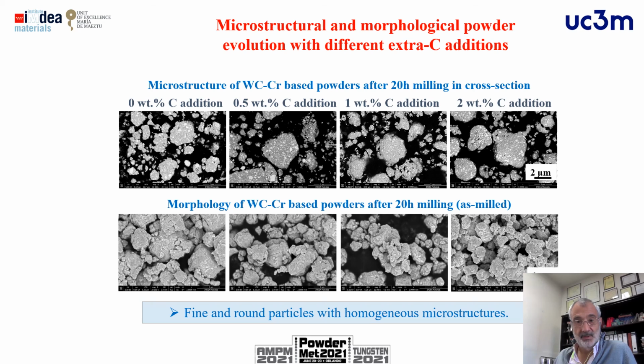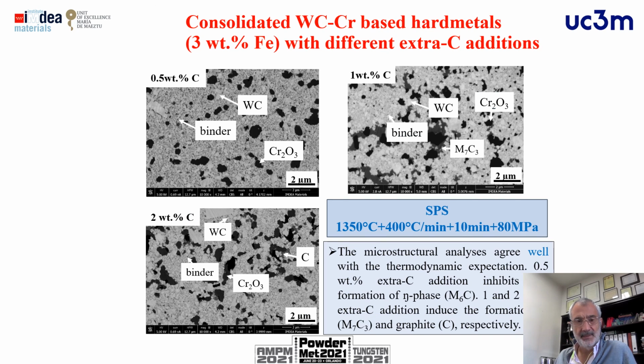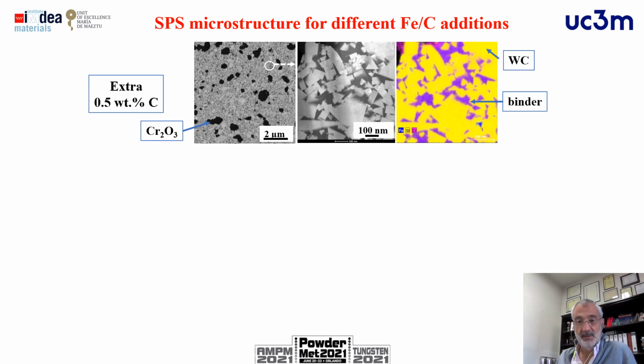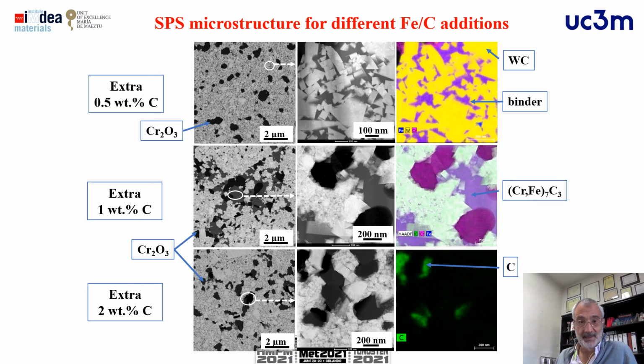Here we have the evolution of the mechanical milling. At the end, we also got, after 20 hours of milling, these rounded particles. The microstructure with the different carbon additions also presents some levels of chromium oxide, but as much as we increase the amount of carbon, we can have also these carbides which are not desired due to the brittleness that can be introduced with this percent of carbons. Here we have also, with more detail, what is happening in the microstructure with an extra amount of carbon over 1% or 2% with these new carbides that can be established.